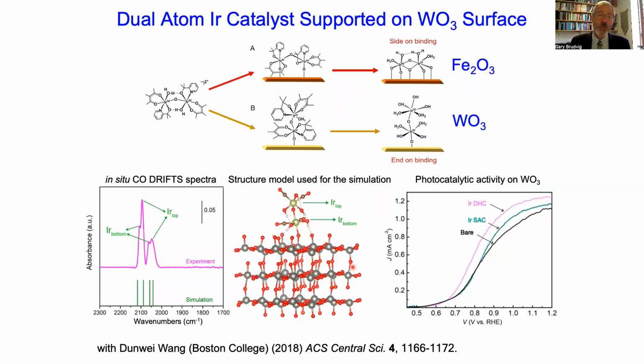We can put it on other surfaces as well. And we've looked at, for example, tungsten oxide. The interesting thing about tungsten oxide is that its lattice is larger. The lattice spacing is larger, and it doesn't allow a side-on binding like we see in the case of hematite. Instead, we see end-on binding. When we image the surface, we don't see dimers, but we see only single bright spots, which we believe is because the iridium catalyst is pointing straight out.